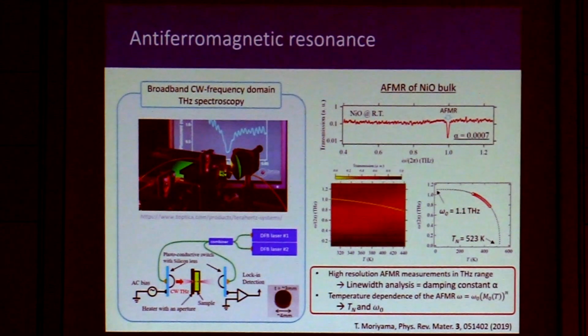If you increase frequency, you're expecting the dynamical damping to increase. As you increase temperature, you're decreasing frequency. But the thermal broadening should increase with temperature. You see things increasing, you associate that with thermal broadening. You see them decreasing, you associate it with the spin pump.